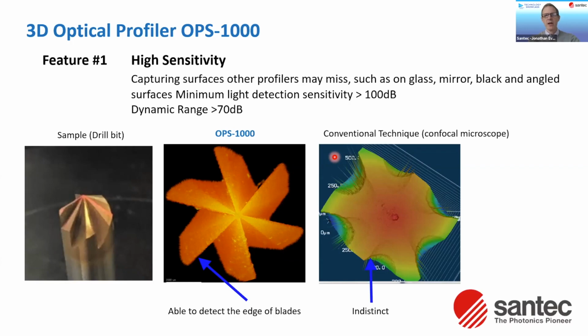And the example I give here is a drill bit. With the OPS, you can see we can distinctly see the edges, or the highly scattering edges of the drill bit, when compared to perhaps a conventional technique of confocal microscopy, where you start to get a blurring of the actual blade surface, whereas it's very sharp in the OPS 1000 image.